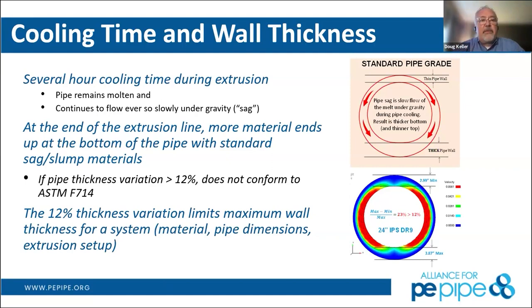ASTM F714, for example, on water pipe and large diameter pipe, says that as a pipe manufacturer, you can have a maximum thickness variation from min to max, that difference in wall thickness, of 12%. Anything above 12% does not conform to the standard. Similarly, it would be the same for AWWA C906. So that 12% thickness variation really limits our maximum wall thickness for a system, and that system being a material, a pipe dimension, and the extrusion setup. Next slide, please.